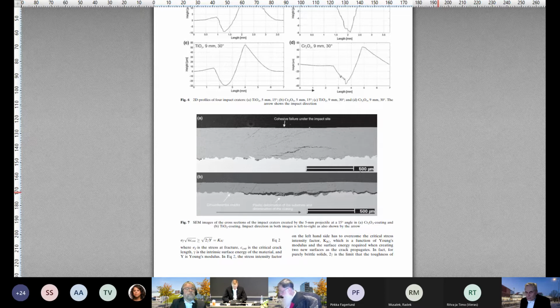Yes, and I try to steer away from direct comparison because of that. We in fact, of course, did the cross section afterwards and saw that it had gone so thin in the preparation for the test. Okay. So at first glance after the test with the profilometer, you do these before you break the crater. You see different behavior and then you cut it open and you realize that it's thinner. So I tried to see what's the good and the bad with each coating individually.